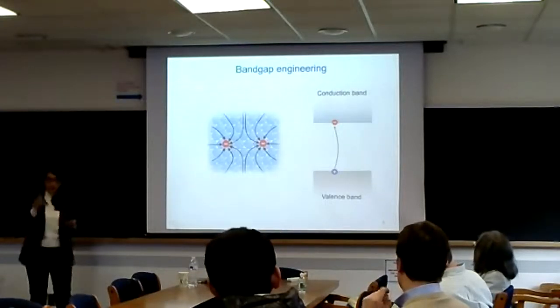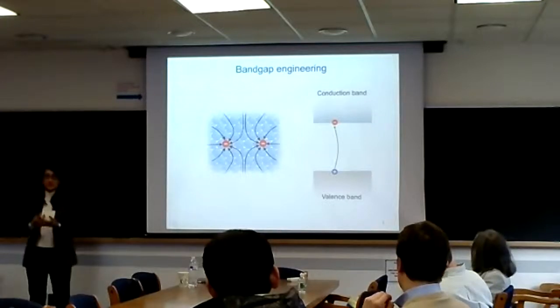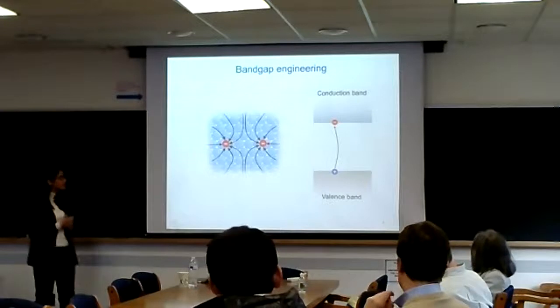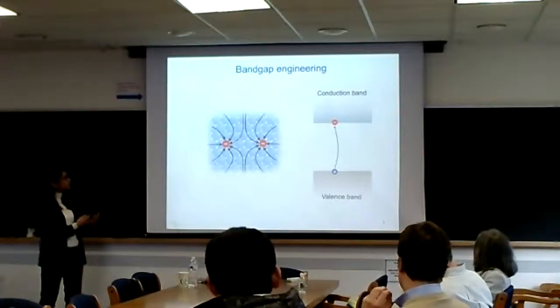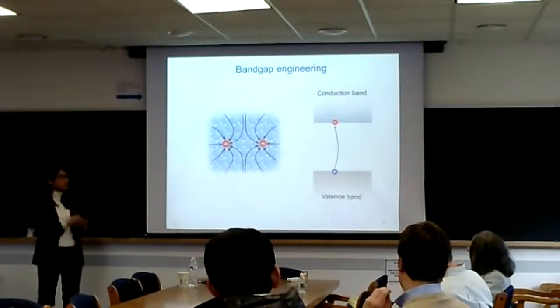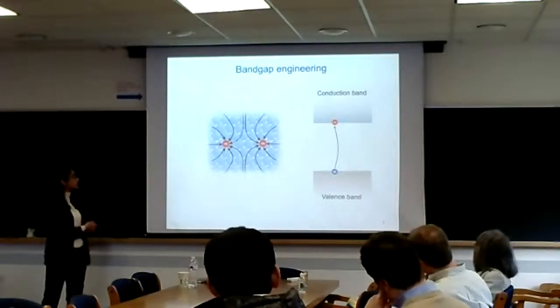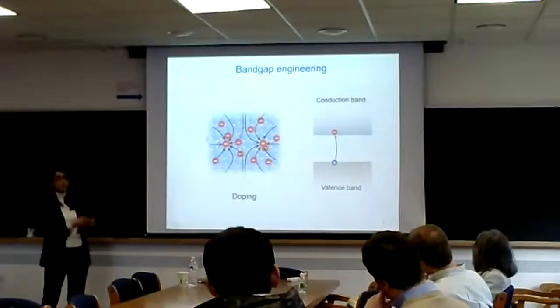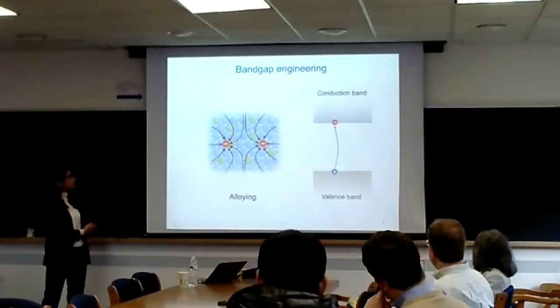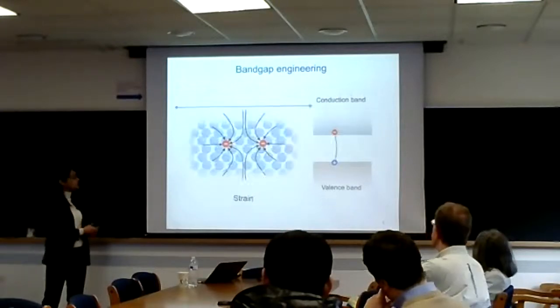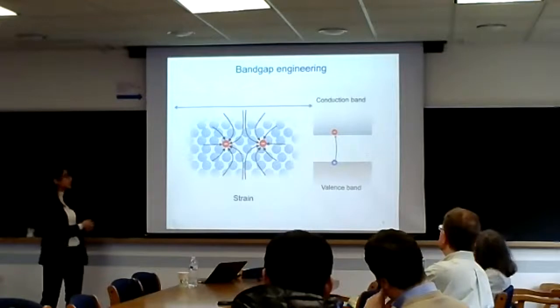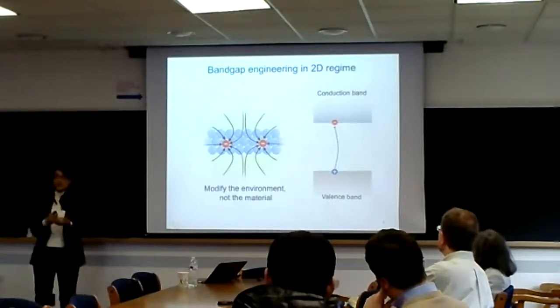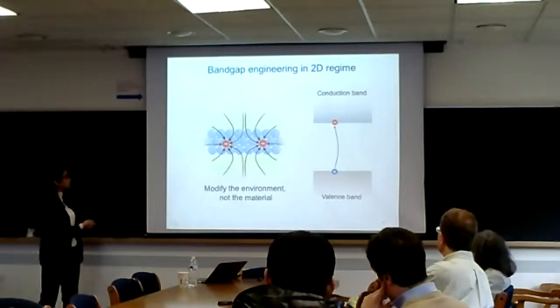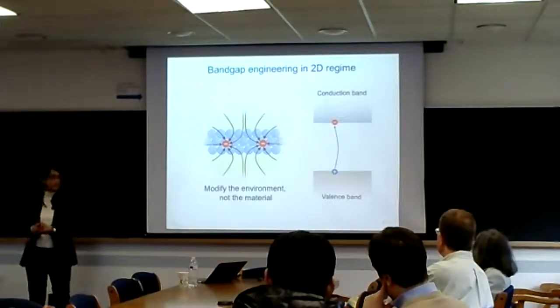So band gap engineering, like the laser pointer that I'm holding today, a lot of the electronics, everything has been driven by engineering the band gap in the solid state. And if you want to boil down to the core of what it is, you have electrons in your band and you're tuning the interaction between these electrons, you can change the band gap. So this is just a cartoon of field lines between two electrons in the material. And in the bulk case, if you were to dope it, you can screen this interaction, change the gap. You can alloy things, you can change the gap that way, or you strain the lattice, and that also leads to band gap engineering. However, at the 2D limit, you can do nothing at all to the material, but just change the environment, because you can see that these cartoon field lines are just leaking out of your system, and you can change the electronic properties of the material this way.